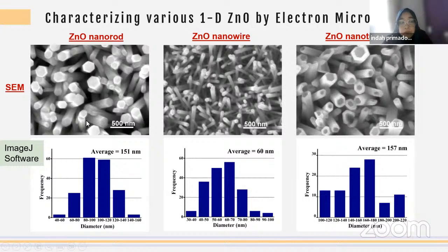you can process your data, or you can calculate the average diameter of your zinc oxide nanorod, nanowire, or nanotube using the ImageJ software. So here you can see the average of the nanorod is 151 nanometer. Nanowire is smaller than nanorod, 60 nanometer, and the nanotube here 157 nanometer. You can see here the nanotube, there is a hole here.